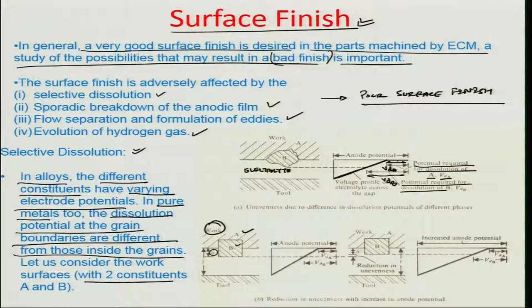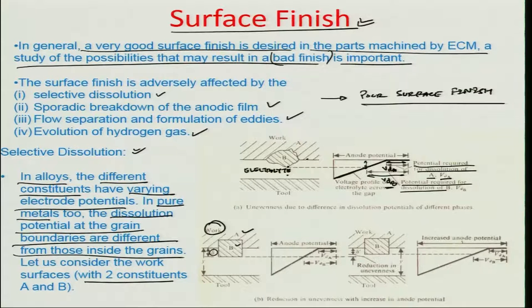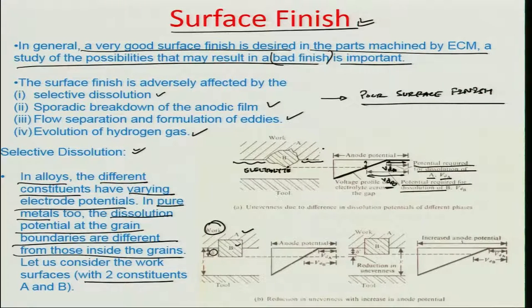We presume there is an ohmic drop in the electrolyte across the inter-electrode gap, shown as a straight-line drop between the cathode and the anode. The available potential VdA, which causes the start of dissolution of phase A, is available at the anode surface. But the potential VdB is achieved further inside the gap due to the voltage drop. Therefore, phase B would start dissolving much earlier, from a point projected closer to the tool, compared to phase A. There is thus a tendency for surface roughness because B is being eroded at a much different inter-electrode gap compared to phase A.